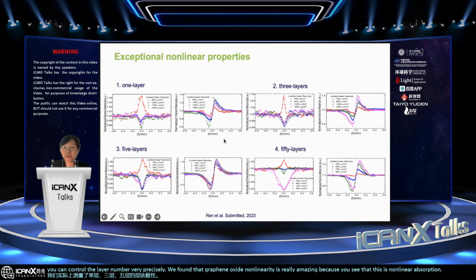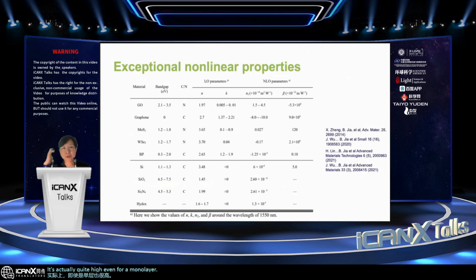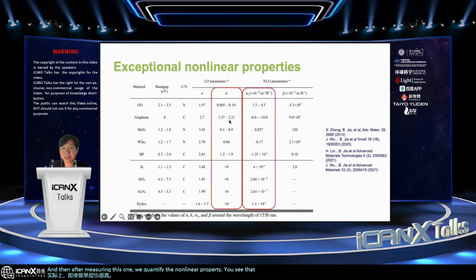It's actually quite high even for a monolayer. And then after measuring this one, we quantify the nonlinear property. You see that this is basically the linear absorption, and then this is the nonlinear refractive index. And we found that because we want to achieve that low linear absorption to reduce loss, in the meantime, we want to have high nonlinearity, therefore enable all these all optical devices.